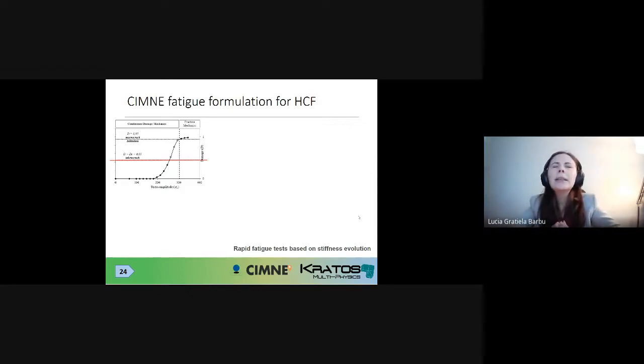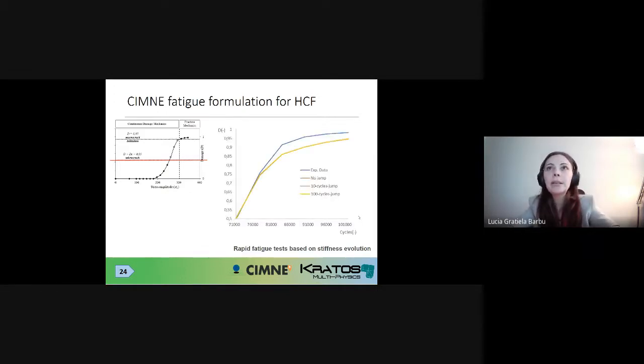In the numerical and the experimental analysis, they were able to detect an increasing level of structural damage. What I mean with this is they computed a specific damage parameter based on the evolution of the stiffness. This is to be understood as a macro structural damage. It's not similar to the integration point damage that you would see in a constitutive law. And we wanted to see if at structural level of the sample, we were able to obtain the same behavior.